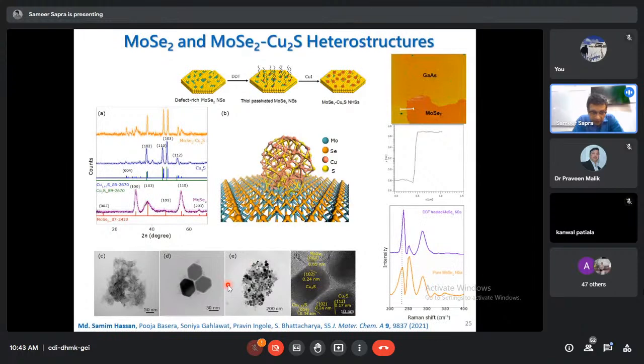You look at some of the TEM images, molybdenum selenide, cuprous sulfide made separately, okay, in the absence of molybdenum selenide. And this is when they are made using the technique I've just discussed above over here, and very nicely characterized. Also with AFM, you can see these are all single monolayer molybdenum selenide corresponding to about 0.7 nanometers height.